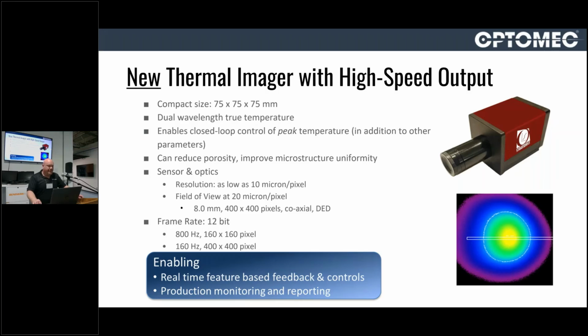The interesting thing is when you're using a melt pool sensor on the center of the part, you get a nice full reflected image of the melt pool back. When you're on the edge and part of the laser is falling off the side, the area method doesn't work as well because you'll never get a full melt pool area back on a contour. Whereas the temperature of the material should still be the same for the contour and the inner fill portion. The thermal imager will allow you to do that. Both the melt pool sensor and the thermal imager, we've tied laser power, powder feed rate, and position, so that the data log of your temperature mapping can actually generate a 3D model that tracks the temperature of the part.